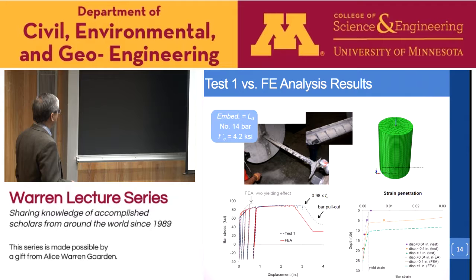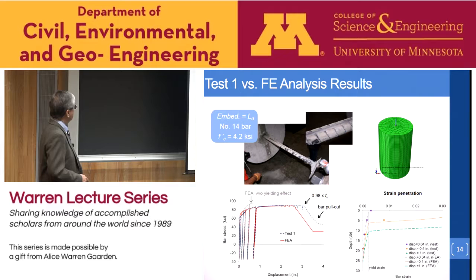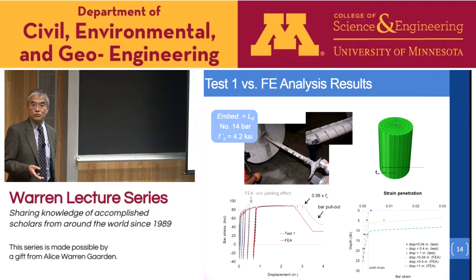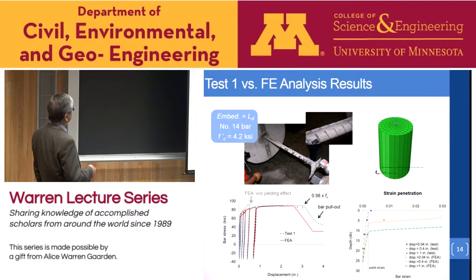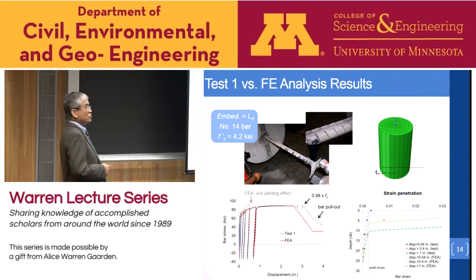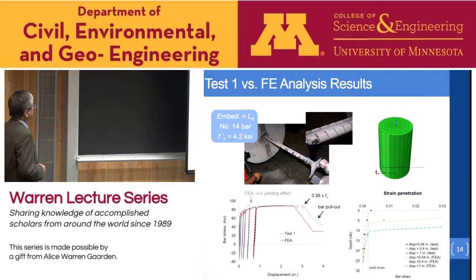Now, you see that we subject it to tension, and then we unload it and subject it to some compression, and then we subject this bar to a number of cycles. So interestingly, eventually what we observed in the test was a bar pull-out failure, you can see in this picture, okay? So all the concrete between the bar ribs was crushed, and the whole bar was pulled out because of this crushing failure, okay? So actually, in that case, the development length was not sufficient to develop the full tensile strength of the bar. So this can be attributed to the fact that this concrete did not reach 5,000 psi, okay? So this shows that the AASHTO recommendation really does not provide sufficient reliability to develop the full tensile strength. So that's what we have found.